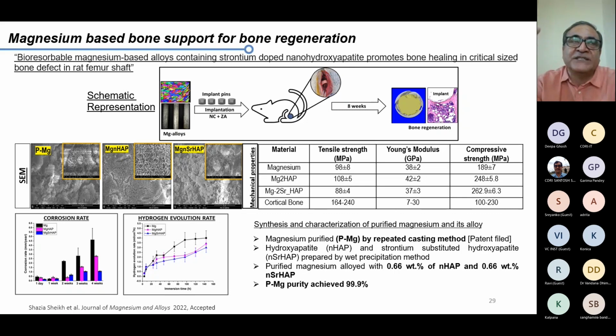But we took a challenge to make very specialized, custom-designed furnaces to generate this type of magnesium alloy here at IIT Kanpur. On a small scale, we have been able to generate these magnesium alloys and also to purify the magnesium which we have been buying commercially, by a simple alloying process. If you have a high degree of purity of magnesium, the corrosion rate and degradation rate can be controlled. We have also been alloying it with other components, like HAP, hydroxyapatite, and strontium HAP. I'm just giving a glimpse of the overall results which have come out.